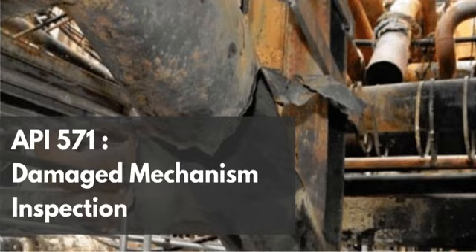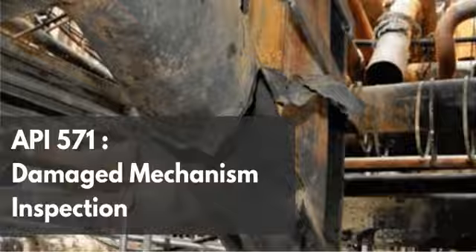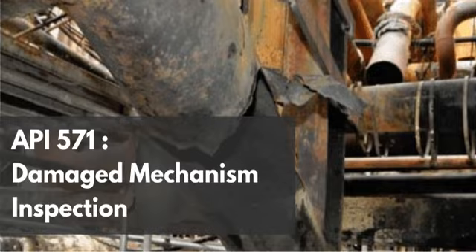But practically speaking, you cannot take a 36-inch active pipeline out of the pipe rack and put it in a furnace to heat treat a tiny bracket weld. No, you have to perform a local PWHT in the field using ceramic heating bands wrapped around the pipe. And the text provides strict rules for this, referencing NACE SP0472 and WRC 452. Right. WRC 452 dictates the mathematical modeling of the required heating band width. This is critical to avoid creating new residual stresses.